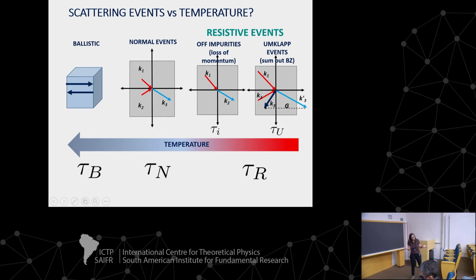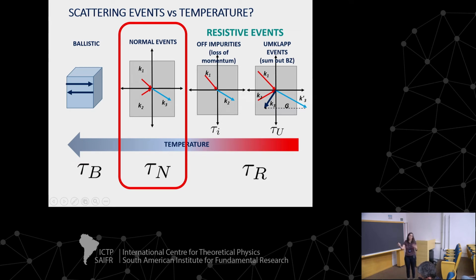And finally, sorry to have both representations, the real and the reciprocal, but ballistic is just because it represents better that we are limited by the physical geometry of the material. So this is, from a qualitative point of view, what we need to look at to have hydrodynamics of phonons, the very efficient transport regime. Are these three tau in this order? Clearly not. Otherwise, the papers that I have mentioned before, with a different hierarchy of scattering, would not make sense. They would be fixed like that. Between the boundaries of these three, we can have a different hierarchy due to some characteristic of the material. But definitely it is something that we expect not at high temperature at the moment. It would be good to have this regime at high temperature.